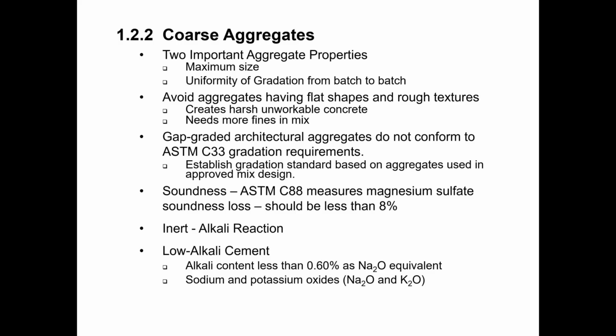So there are a variety of ASTM tests that can be used to evaluate coarse aggregates, just like we can evaluate fine aggregates. One way that we can offset the potential for that alkali reactivity is to use a low alkali cement. To qualify as low alkali, a cement has to have a sodium and potassium oxide equivalent of less than 0.60%.